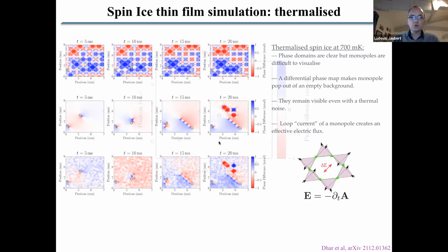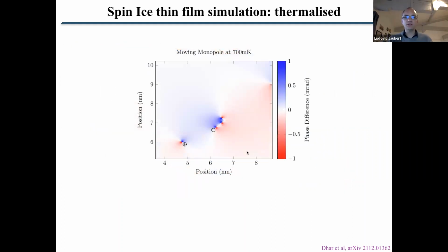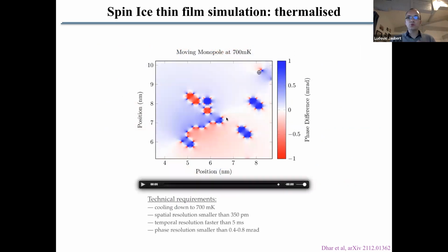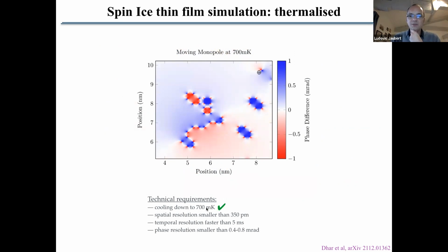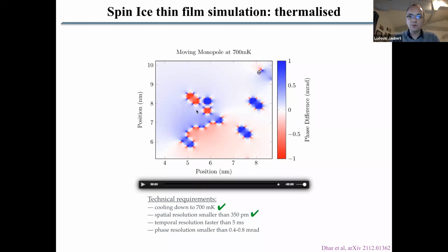So now, this is a small video of what happens. Ideally, this is what you will be able to see in experiments. And now about technical requirements: cooling down the system to 700 millikelvin, because that's where you can see monopoles in spin ice. That should be possible. I mean, it has not been done, and it's not in any electron microscope, but there is no scientific difficulty for that. A spatial resolution of 350 picometers, that's what we need to be able to see these islands, these monopoles, and that's available with the best TEM machines in the world.